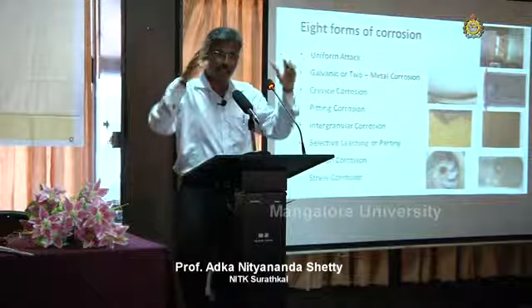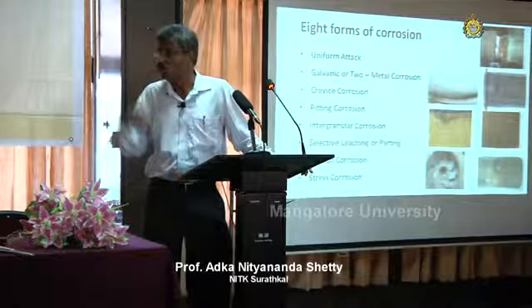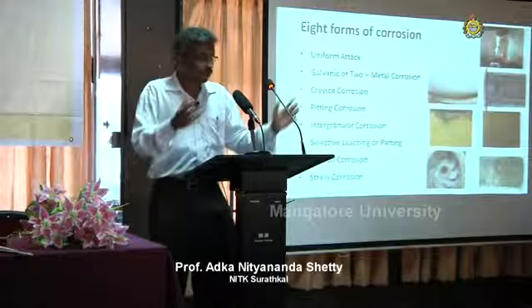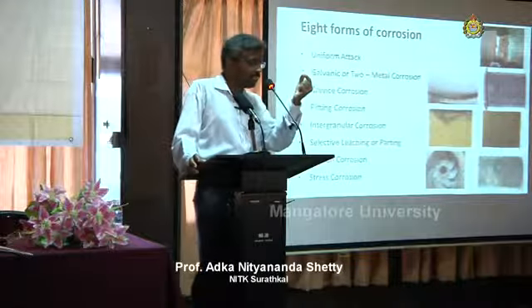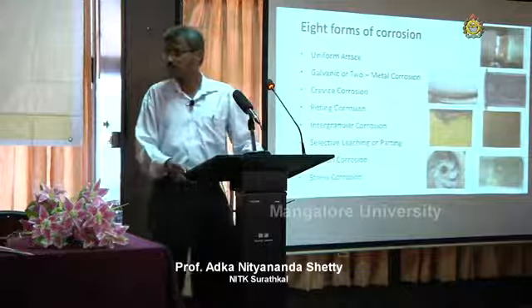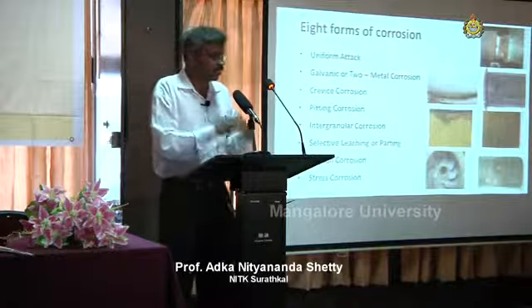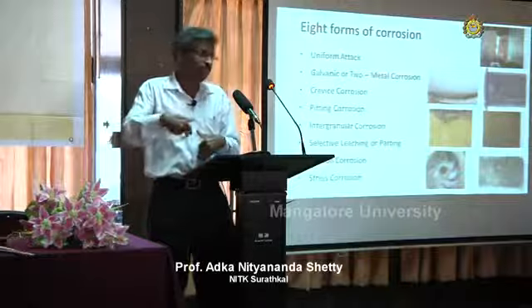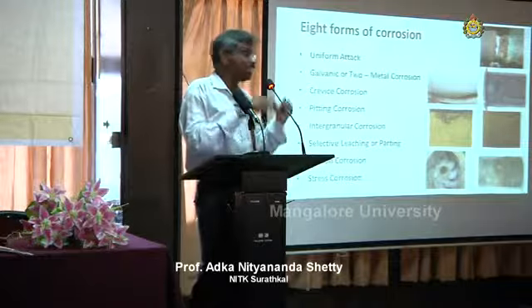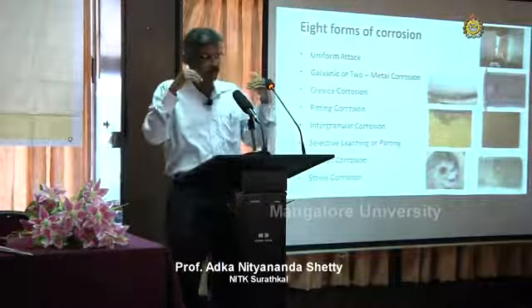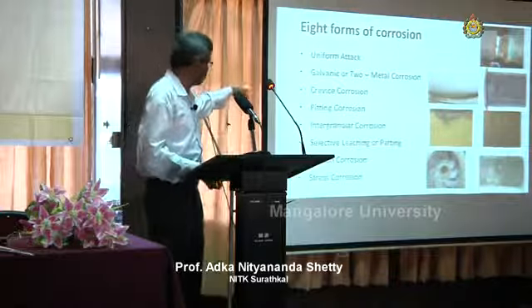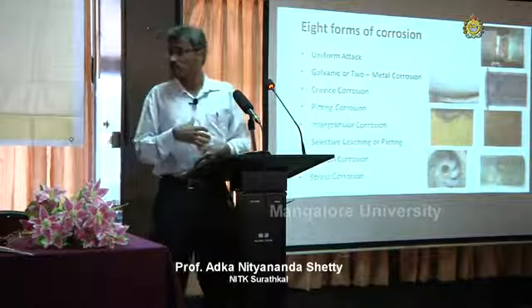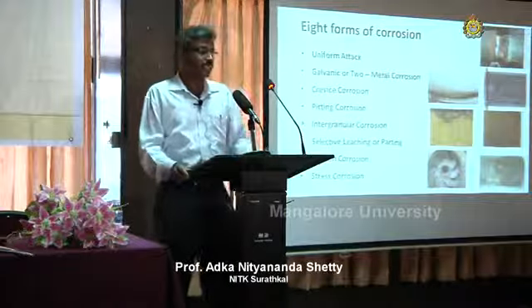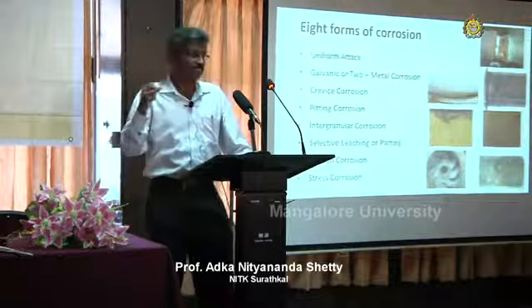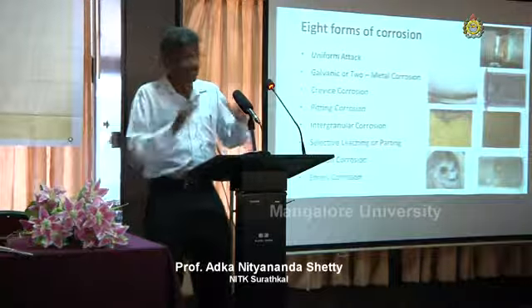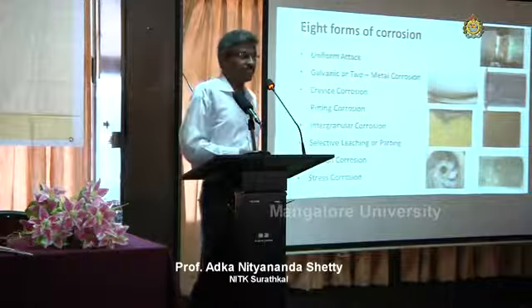If there is a metal structure, you will come to know that the metal has undergone pitting corrosion only when the structure fails or it falls down, because they will be forming very micro pores, minute pores, and generally that will be covered with the corrosion product and we can't see it, and this will be vertically migrating into the structure, making the metal weak, and under load it can collapse at any time. Similarly, the intergranular corrosion, the metals are made up of grains, crystalline grains. At the grain boundaries, the metal can undergo corrosion.